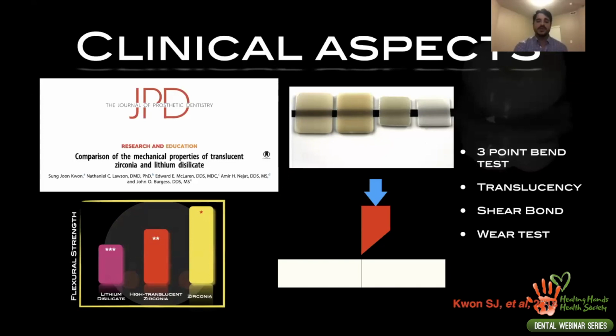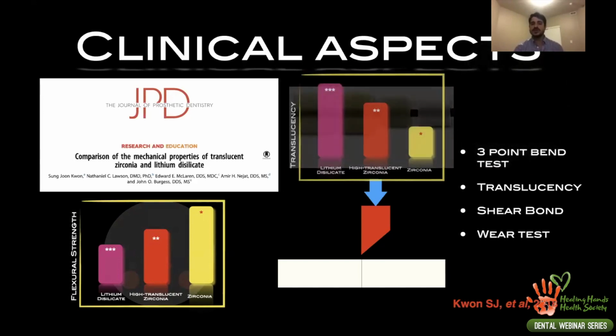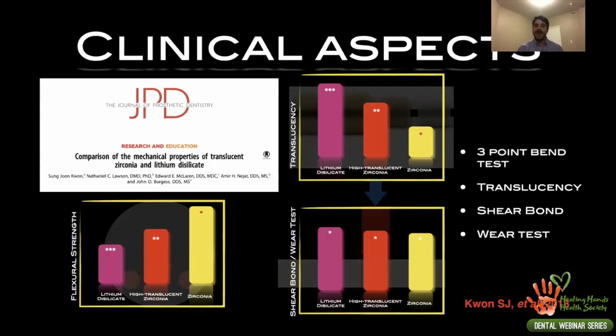When we talk about flexural strength, we have conventional zirconia significantly stronger than the high translucent zirconia, which is again significantly stronger than the lithium disilicate. Whereas when we look at translucency, lithium disilicate is a lot more translucent than the conventional zirconia and the high translucent zirconia. And the bonding and the wear pattern of those three materials are fairly similar. Again, this is an in vitro study, so some of these numbers have to be carefully evaluated when translating them to the clinic, but it shows a pattern of what we see in the clinic as well.